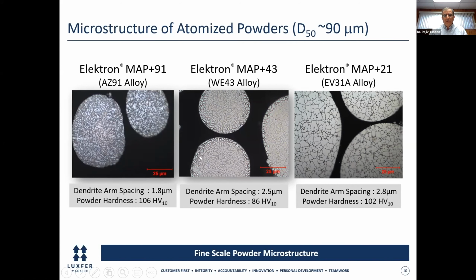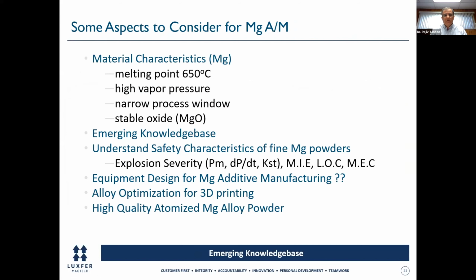So this is an example of powders all in the 90 micrometer diameter range, which showed dendritic arm spacing of around 2 micrometers. But you can well imagine if you were to go down to mean particle sizes of about 30 to 35 microns, which is what is used in additive manufacturing, you're looking at very, very fine scale grain sizes of the order of maybe less than a micron to around a micron, which gives you a really good starting point to be able to preserve the grain structure in your process and therefore achieve significant property enhancement over what you can normally achieve, say, by casting, for example.